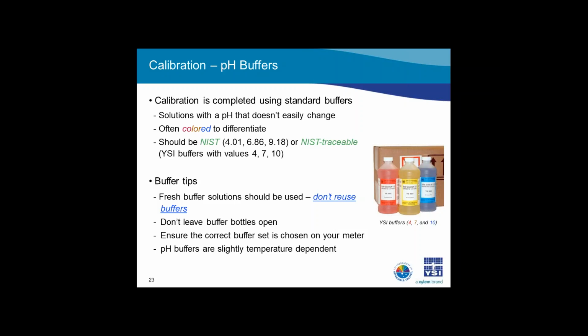It is also important to note that pH buffers are slightly temperature dependent, so the actual pH value of the buffer varies with temperature. For example, the actual pH of YSI buffer 7 at 20 degrees C is 7.02, and at 25 degrees C, it is 7.00. pH buffer values based on temperature can usually be found on the bottle or certificate from the buffer manufacturer. For maximum accuracy in your pH measurements, be sure that the auto buffer recognition is adjusting the buffer value based on temperature, or override the calibration value with the correct temperature adjusted value. All of YSI lab and field instruments have buffer values based on temperature pre-programmed into the instrument software in the auto buffer recognition feature, and these temperature corrected values are used.